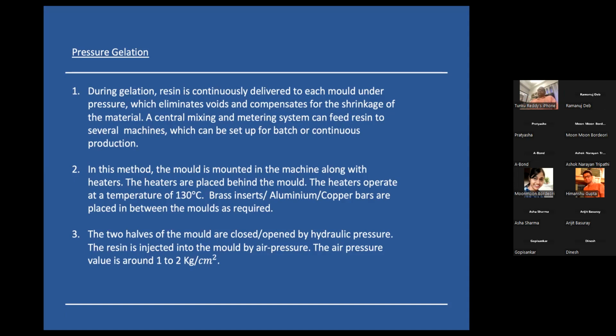In this method, the brass inserts are placed between the molds as required. Both halves of the mold are closed under a lot of pressure by hydraulic pressure. The resin is injected into the mold by air pressure. The air pressure value is around 1 to 2 kilogram per centimeter squared.